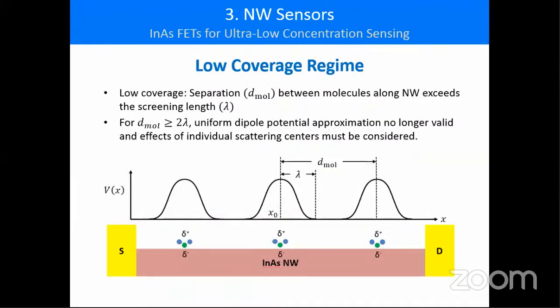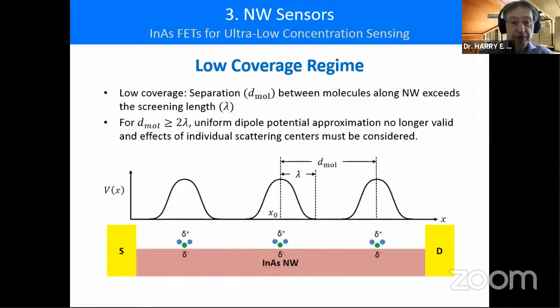So that brings us to what I said was the purpose of the exercise, right at the beginning of this section, which is to show if we can come up with paradigms in the nanowire case for ultra-low concentration sensing. And that means single molecule type of level. In that case, we're no longer talking about a uniform dipole layer or sheet of charge. We're talking about individual scatterers effectively, as far as molecules coming in and affecting transport in the channel of the transistor. So in this case, we're talking about the separation between the molecules exceeding the screening length, and typically quite a bit. So we say that D has to be greater than or equal to at least 2 lambda in this case.